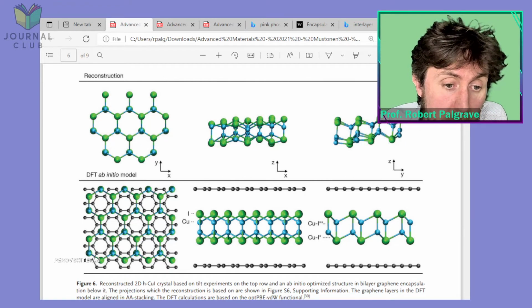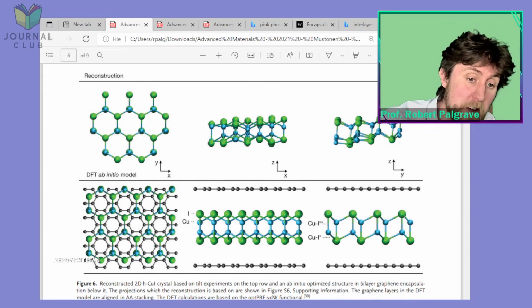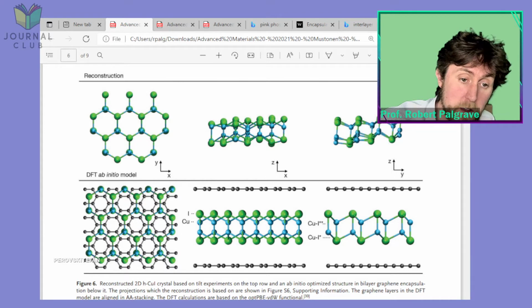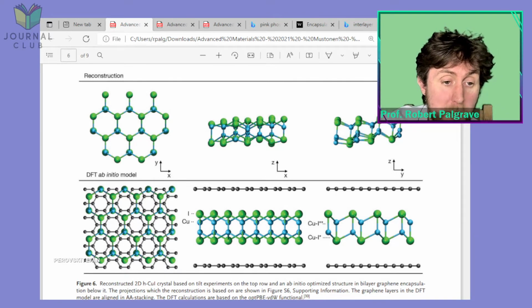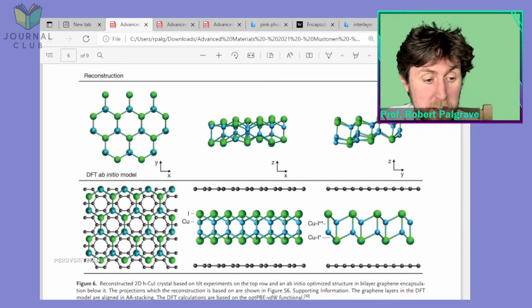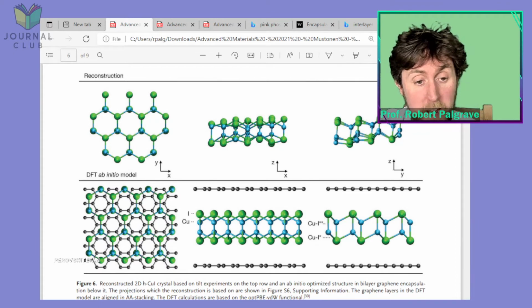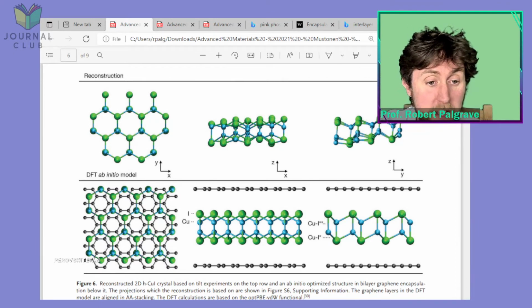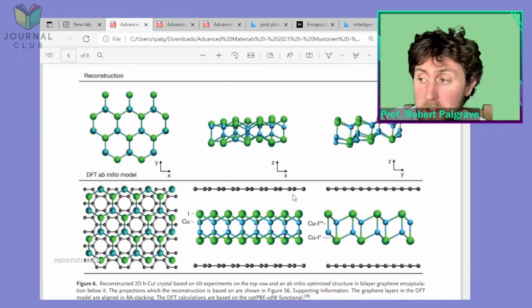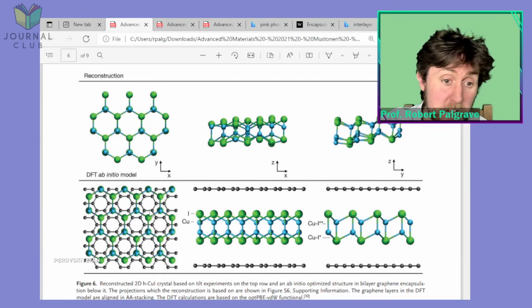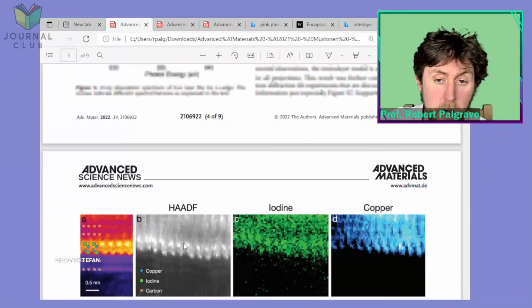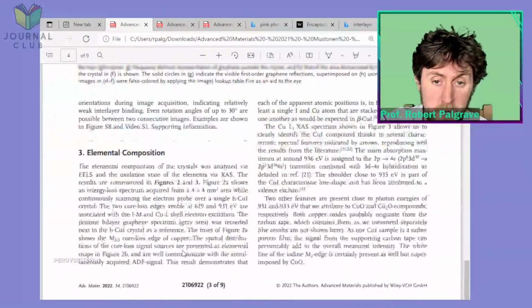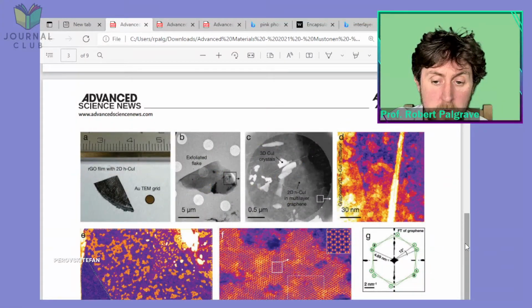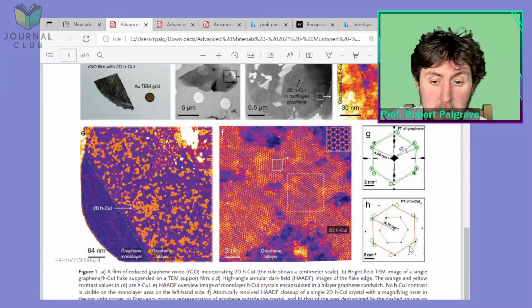You can see here the in-plane interaction with the graphene, which is the black spheres, and the relationship between the lattices in the graphene compared to the lattice in the hexagonal cuprous iodide. So again, a nice relationship here. This one I'm showing here is the relationship between those two lattices. This is what they were talking about up here with the Fourier Transform. So this is a real space image of this down here.